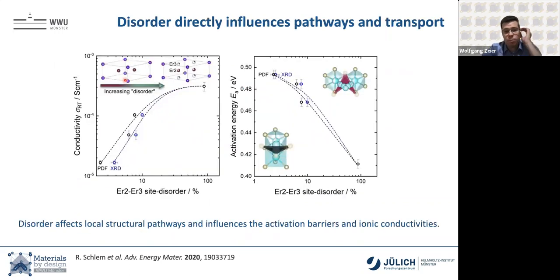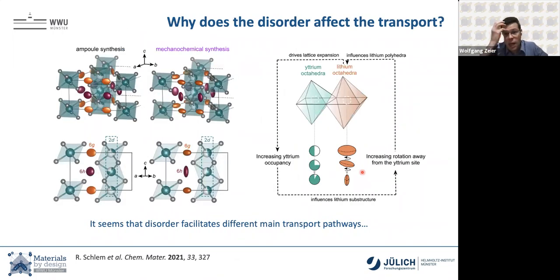And if you then plot your conductivity as a function of site disorder, you see that the more disorder you have, the higher your ionic conductivity. And the more disorder you have, the lower your activation barrier. So really, this disorder directly influences the ionic transport, and milling makes these materials just so much better ion conductors. Why does this really affect the ionic transport? I think right now we don't have an answer yet.